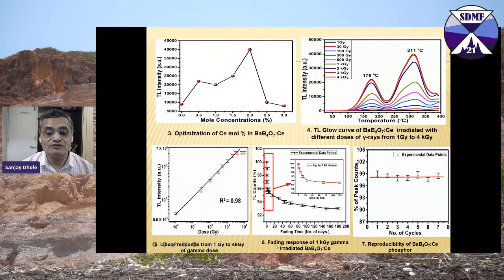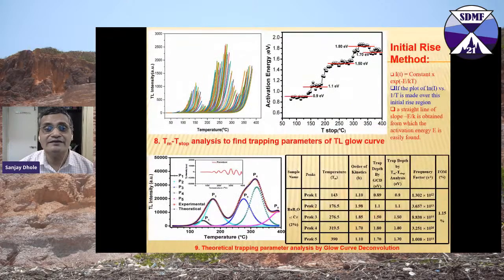And of course, the fading response for 1 kilogray is quite less than 10%. And the reproducibility is quite good. Even if you do the experiment quite often, after 1 or 2 days, the fading is less, and the reproducibility can be maintained. So there is the TM-TStop.